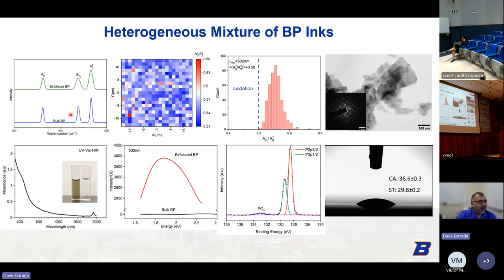And then after exfoliation, we retain the right Raman peaks. We look at the ratio of the A1g to A2g as an indication of oxidation in the phosphorus system. And so here's a nice map showing that the ratio stays well below 0.5, which is indicative of oxidation. We get large crystalline domains, which are shown through the diffraction pattern of TEM. And you can see that they're about hundreds of nanometers on edge.